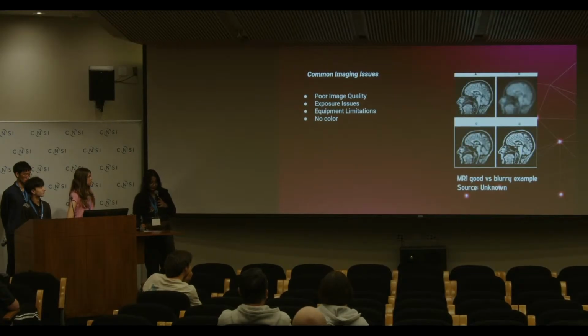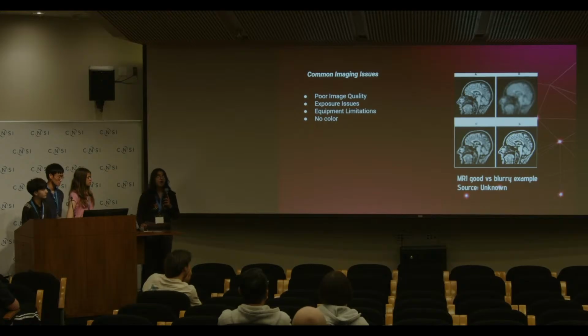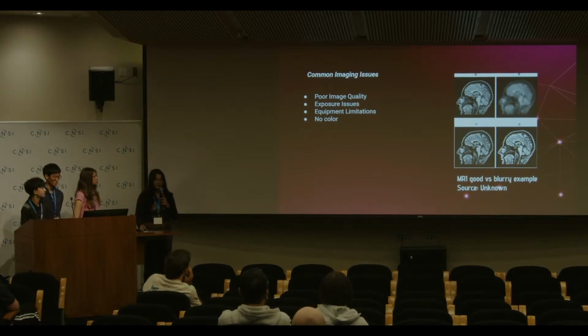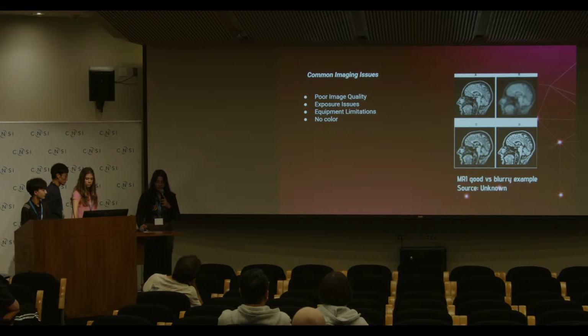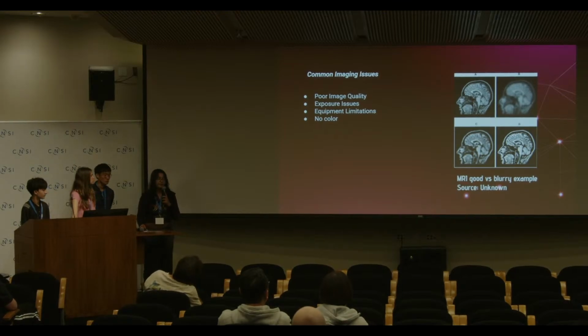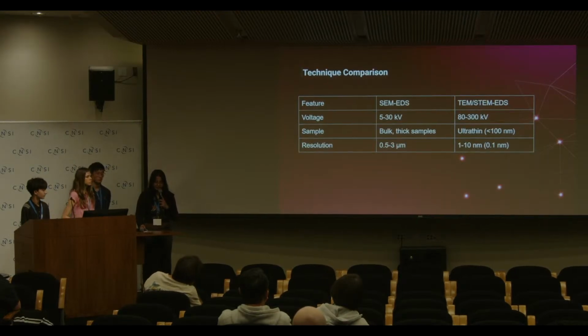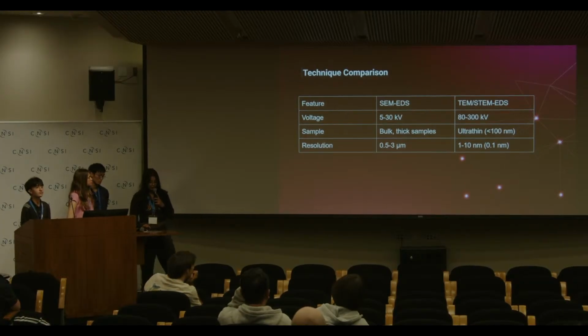So we would ask which tool we should use for operating at lower voltages. SEM EDS uses about 5 to 30 kilovolts, and is perfect for bulky and thicker samples. And it gives us micron scale resolution, which is ideal for routine surface analysis. But when we need to see the atomic world,